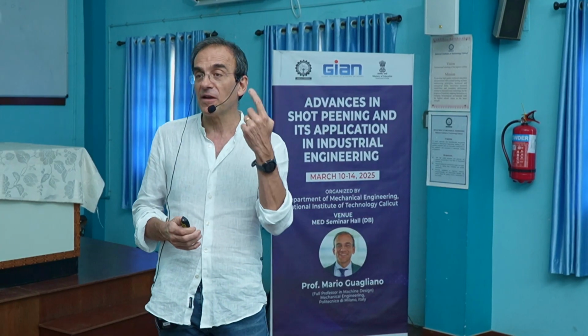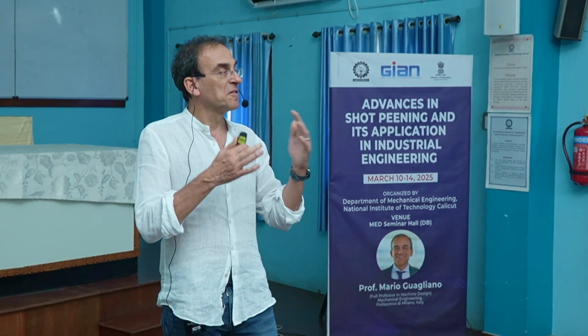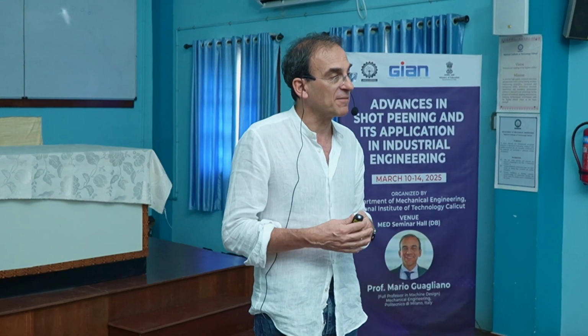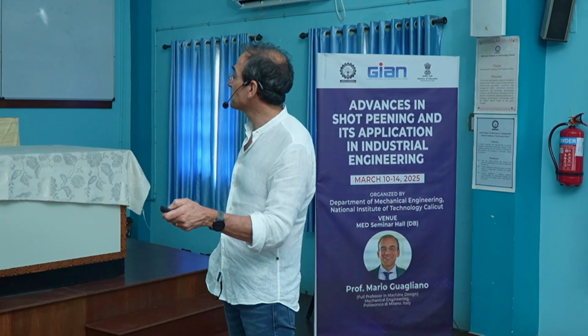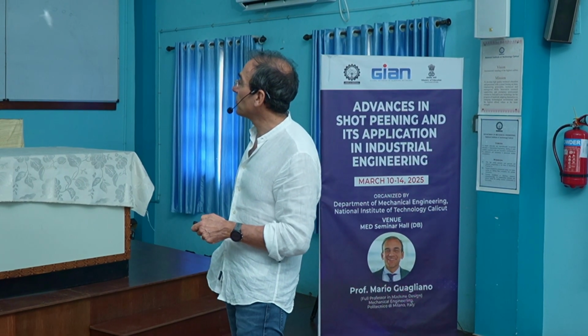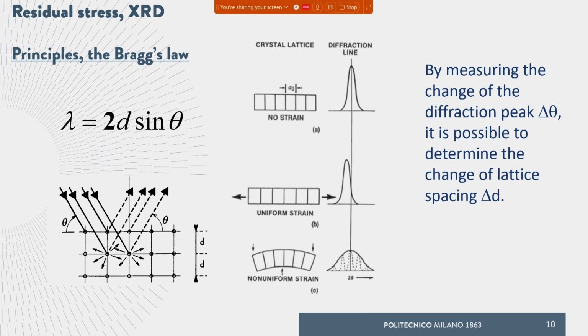That is, not a single line, but a peak whose shape is similar to a Gaussian function. Okay? This is the Bragg law. Imagine here, this is a material we are measuring. We have no strain. The crystal lattice is this. If the material is perfect, we will have one single line. Here the representation is not for a perfect crystal, but almost perfect. We have a very narrow peak.